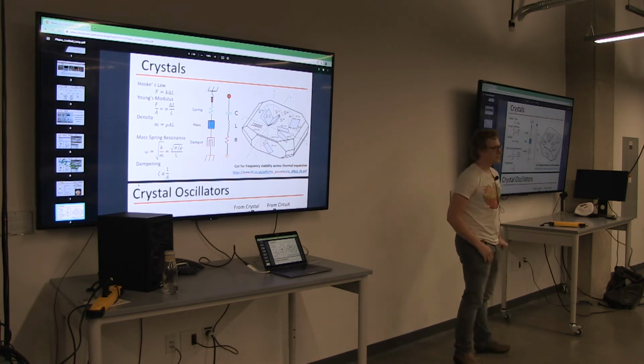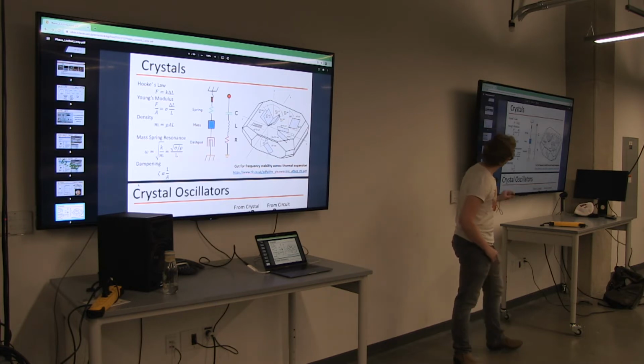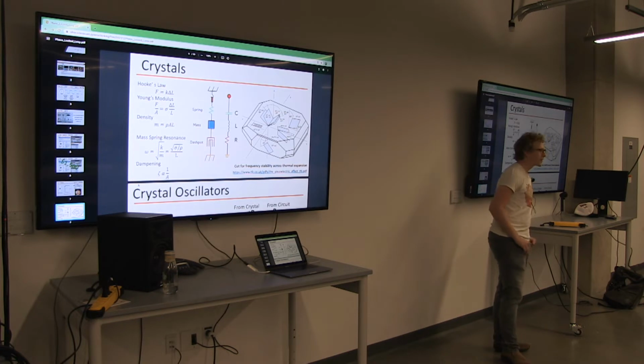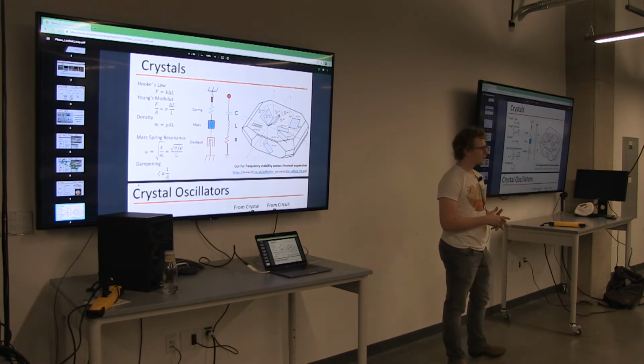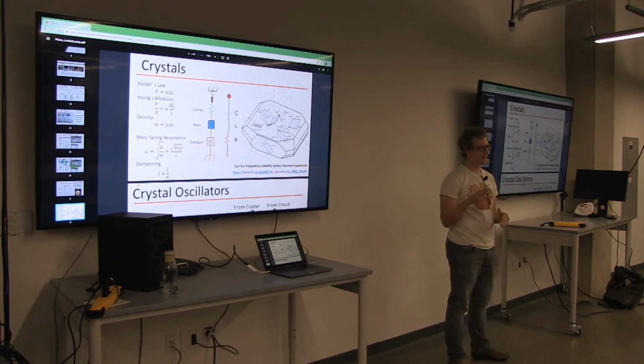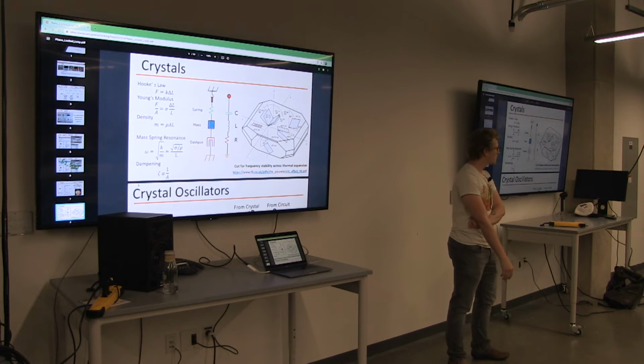So what you want is for the crystal to have the same frequency across a lot of temperatures. And a really popular cut here is this AT cut, this 35-degree cut. What this does is it helps compensate the crystal over the normal operating range for a lot of products. And so you'll go from maybe negative 10C to 85C, and that's what that cut is really good at. Because quartz in particular is really well compensated, where it doesn't have a lot of temperature variation with frequency between like 0 degrees C and 50 degrees C, but these cuts make them much more stable.